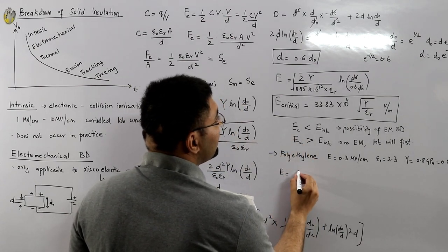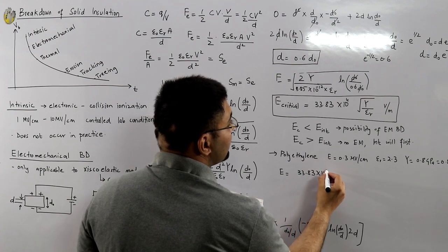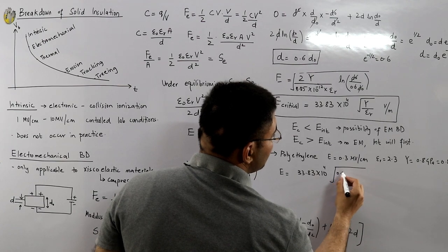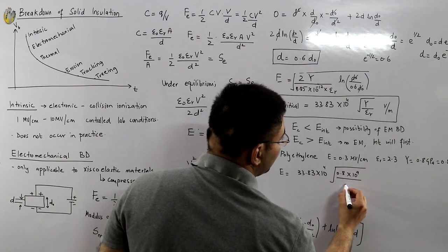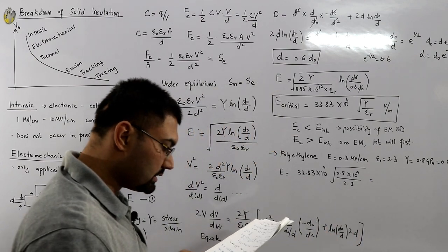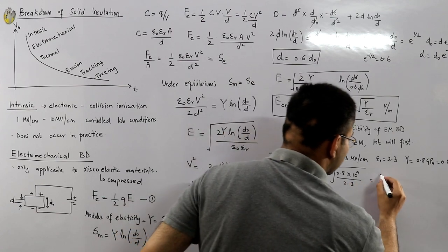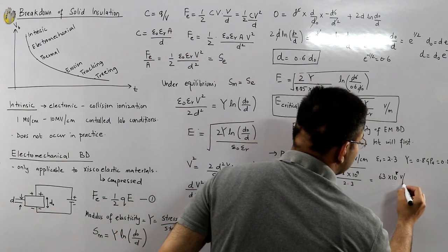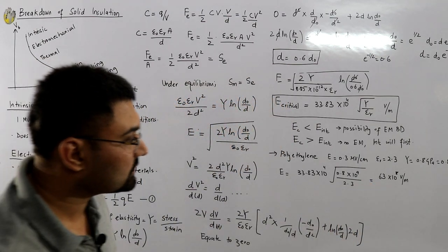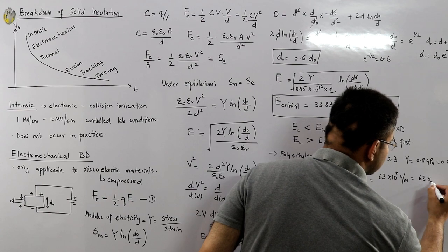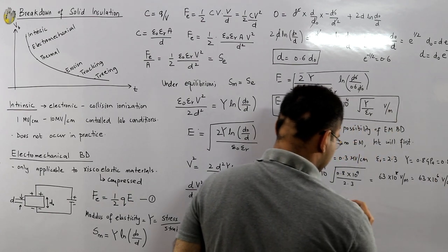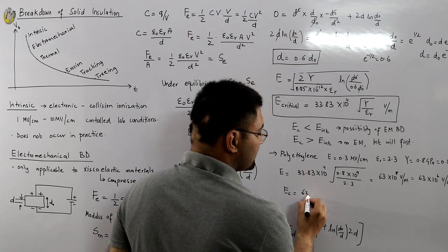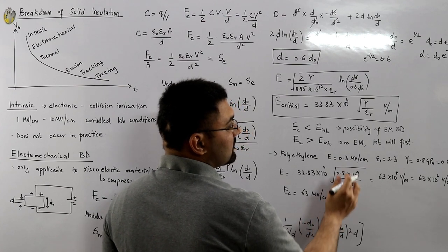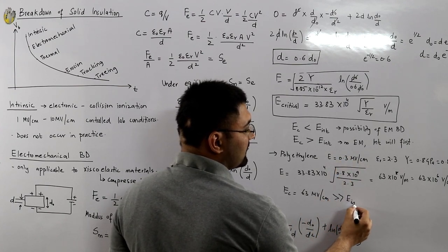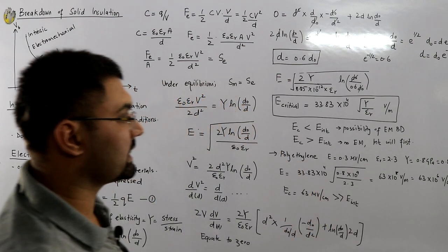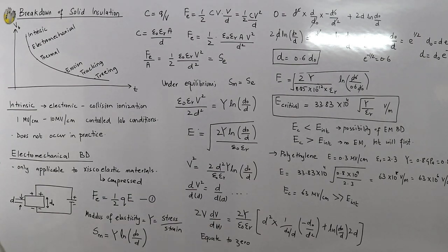You find out the critical field, which would be 33.83 into 10 to the power 4 multiplied by 0.8 into 10 to the power 9 divided by 2.3 under the root. Do the calculations. The critical value comes out to be 63 into 10 to the power 8 volts per meter, or 63 into 10 to the power 6 volt per centimeter. Or I would say that the critical field is 63 megavolt per centimeter. So have a look. This is far greater than the intrinsic field, which means that there is no possibility of electromechanical breakdown, which means the intrinsic breakdown has already occurred.